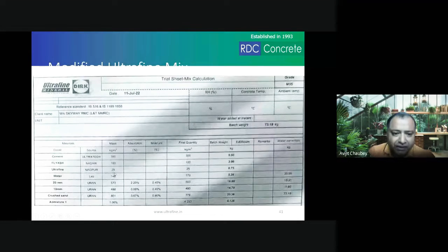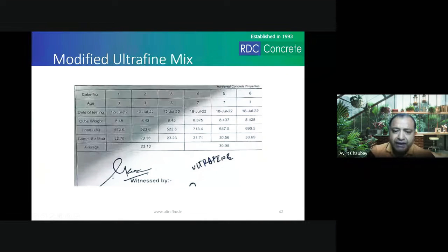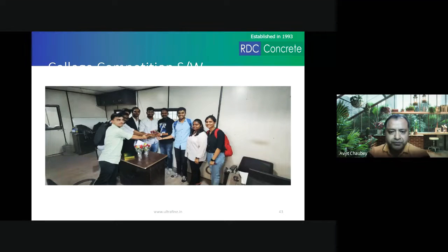Now, if you see, with ultrafine, the cement content was reduced to 300 kgs and ultrafine was incorporated of 25 kg, and they have been able to get 31 MPa in 7 days and 23 MPa in 3 days, almost the similar strength or better strength, not similar but better strength. But I would be rather humble and call it the same strength.